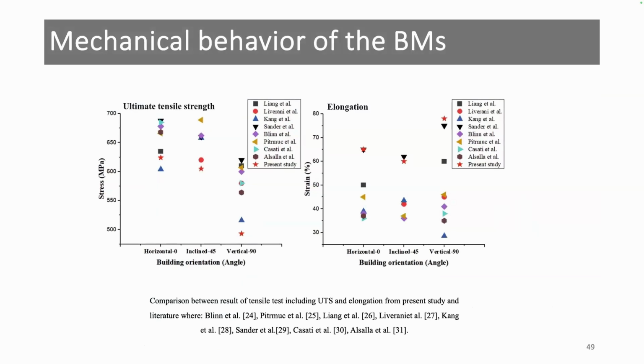Here we compare the values of strength and ductility of the printed base metals with the literature. For this one, we find that the strengths of 0 and 45 were greater than the 90 degree specimen, and this is in agreement with the literature. While in the elongation percent, we find that the 90 degree orientation gives the maximum elongation percentage, or ductility.